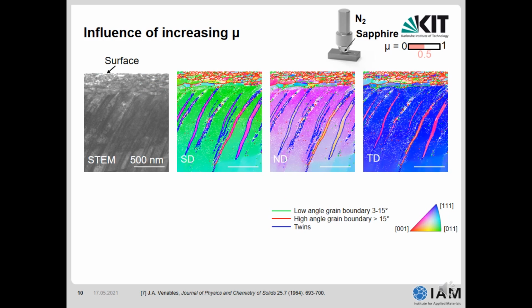Here I would like to show you the influence of an increasing friction coefficient. Therefore, I have changed the counterbody to a sapphire sphere and the atmosphere to nitrogen. The resulting friction coefficient was 0.5 in comparison to 0.2 of the other system. I think it's quite obvious that here the deformation layer is much thicker than in the system before.